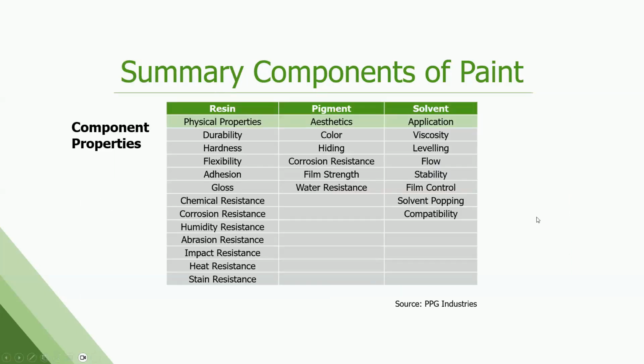So this is kind of a cheat sheet on the components of the paint and what they're bringing to the overall recipe or equation here. So the resin, the polymer: durability, hardness, flexibility, adhesion, gloss, chemical resistance, corrosion resistance, humidity resistance, impact resistance. That's a lot. It's a long list. Pigment, again, primarily aesthetics, but also hiding the substrate. Some corrosion resistance comes from the pigmentation in the primer as well. The strength of the film, some water resistance, of course, UV durability as well.